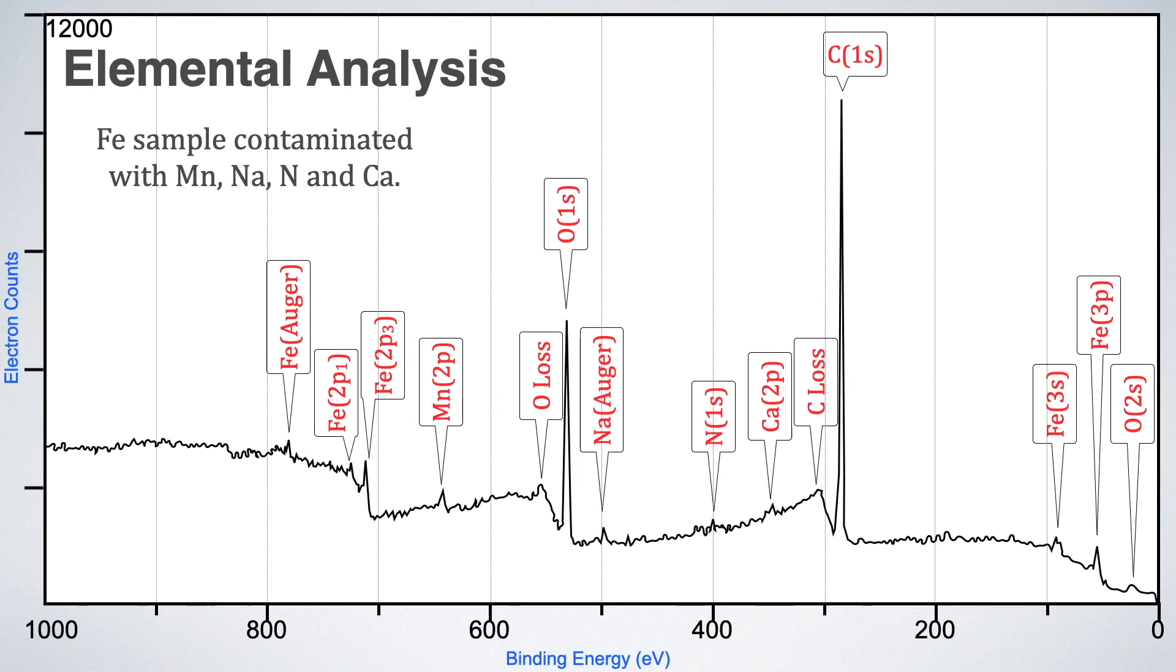Another important application of XPS is to find the percentage concentration of different components present in the sample. Please note that the XPS is only surface sensitive technology and it gives the percentage concentration of sample surface up to a depth of 10 to 12 nanometers only. So, if surface is different than the bulk, it is better to clean the surface very well before analysis.